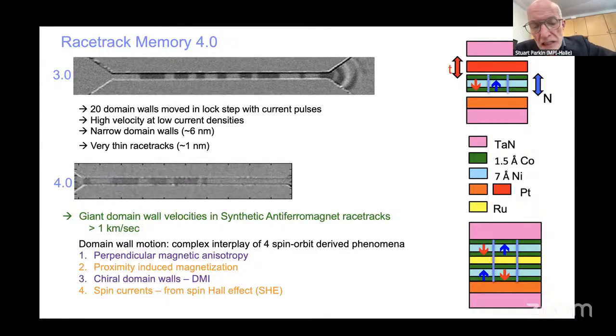And then essentially the motion of the domain walls by current pulses derives from the spin Hall effect in these proximity layers. And I haven't discussed this, but it turns out, very importantly, that the domain walls themselves have a chiral structure due to a so-called interface Dzyaloshinskii-Moriya exchange interaction. I'll come back to this a little bit later. But this chirality is something we first demonstrated, and it's critically important to the motion of the domain walls in a synthetic anti-ferromagnetic racetrack, and in the racetracks 3.0, it means that all the domain walls now move in the same direction under current, but only because the domain walls have the same chirality. If they had the opposite chirality, they would move in the opposite direction.